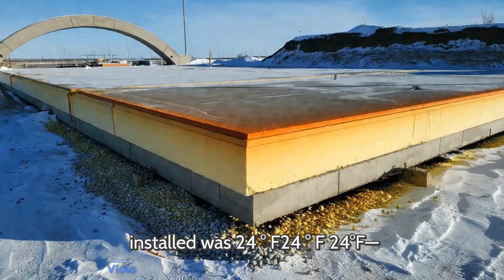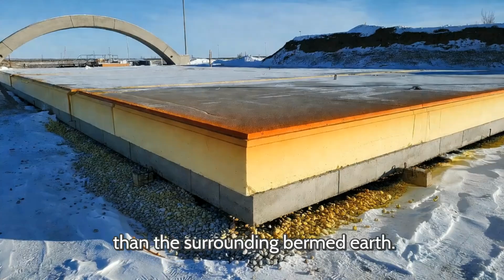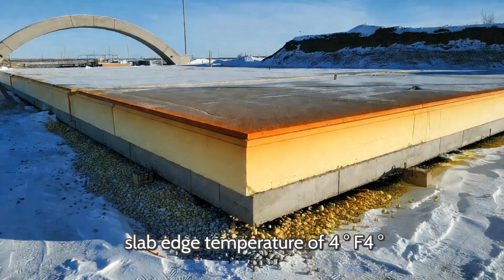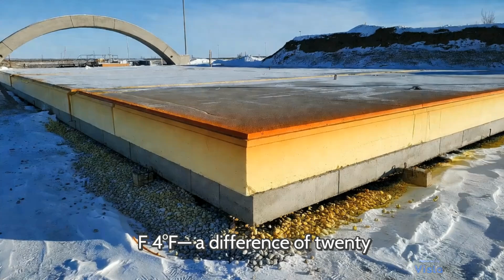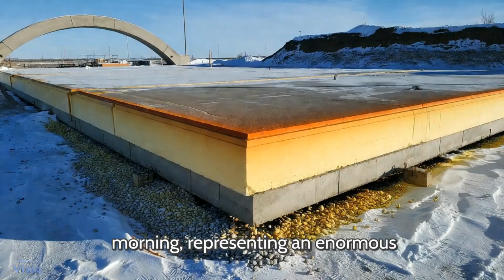24 degrees Fahrenheit, cold, but not dramatically colder than the surrounding bermed earth. At a point near the entrance end of the structure, where the perimeter insulation had not yet been installed at the time of the photo, the same camera recorded a slab edge temperature of 4 degrees Fahrenheit, a difference of 20 degrees in surface temperature on the same slab on the same morning, representing an enormous difference in heat loss rate.